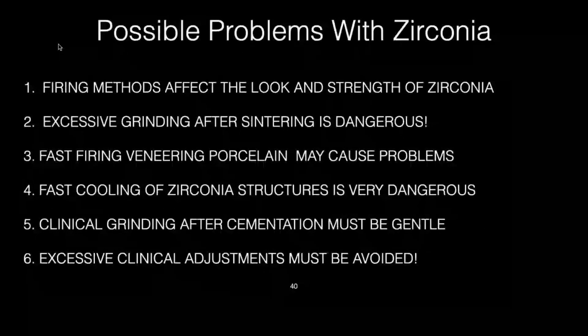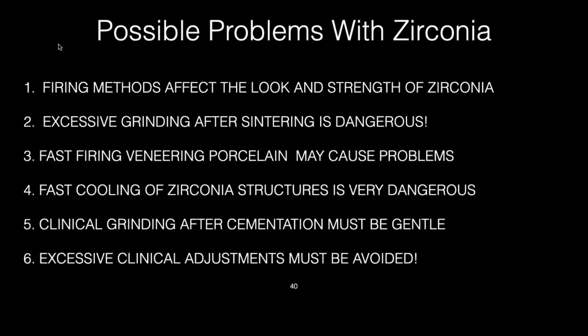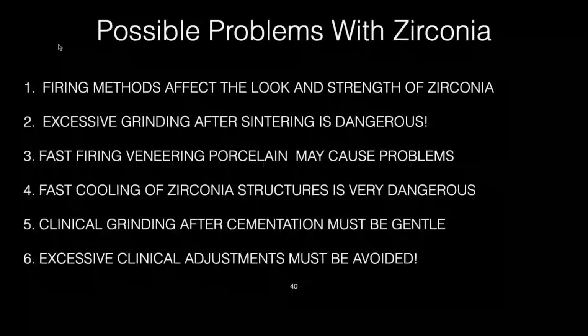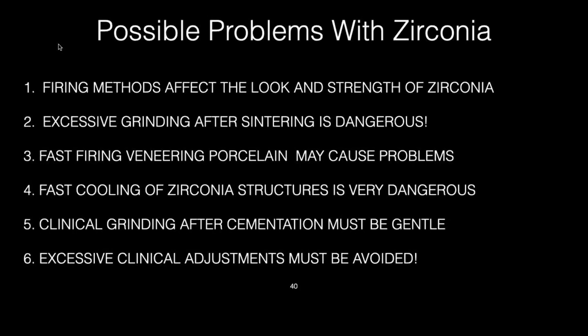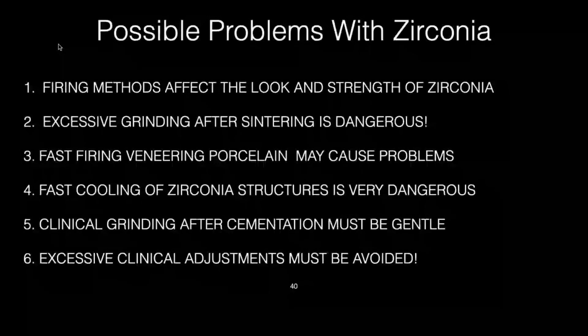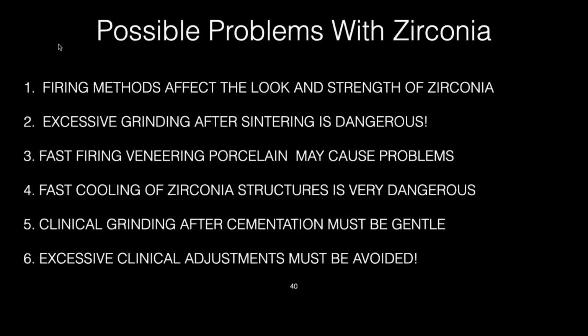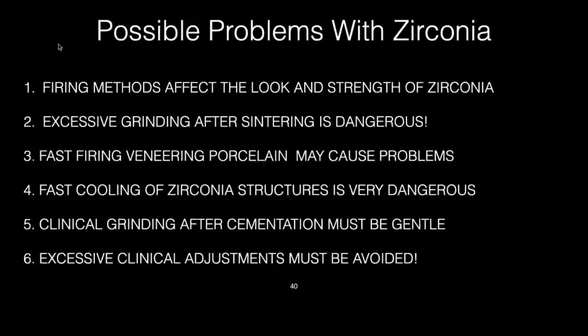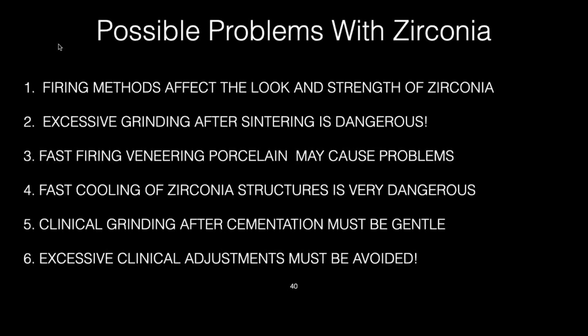And so let's look at some of the problems that you can have in the lab with zirconia. So we know that the firing method can definitely affect the strength. Excessive grinding after you sinter it can be dangerous, no question about that. Fast firing veneering porcelain on zirconia will cause it to lift, and I'll show you. Fast cooling of zirconia is also very dangerous. And the worst is when the doctor grinds it in the mouth after cementation, he better know what he's doing, because he can cause a lot of damage. And they should look at that before they cement it and say, you know what, this is too high or too low. I don't understand how that happens, how you can cement a crown and then grind the heck out of it.